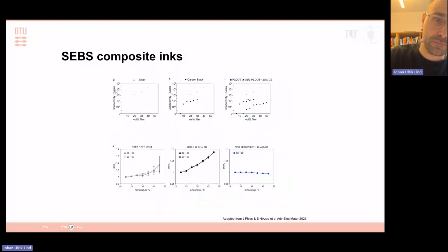So obviously it depends on what you add into your composite. If you add silver particles or carbon black or PEDOT, this is an organic formulation of PEDOT, you get different conductivities, but you also get different sensing properties. One thing we were interested in exploring was whether any of these composites could be used for sensing variables. So obviously strain gauges is an easy use, but we were also interested in seeing, can we record something like temperature?